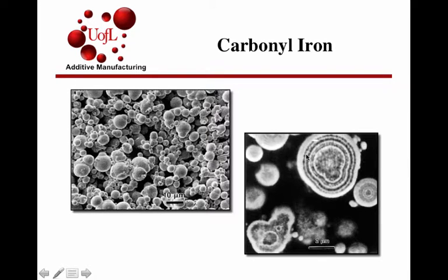Because of this nucleation growth mechanism, if you section any of these powders, oftentimes before annealing, you will see these growth rings as new layers of atoms begin to grow around the core and you end up getting this type of a structure.